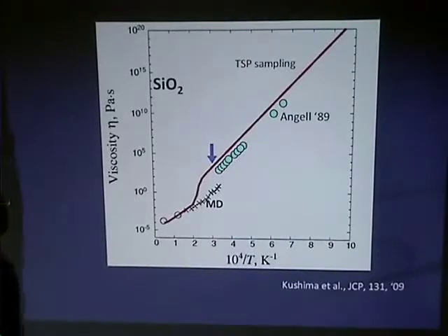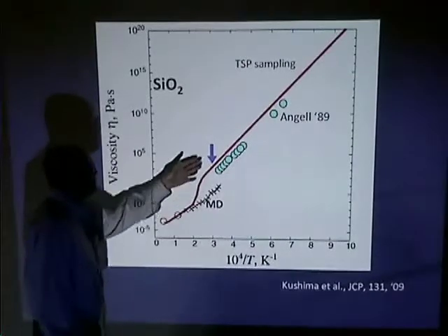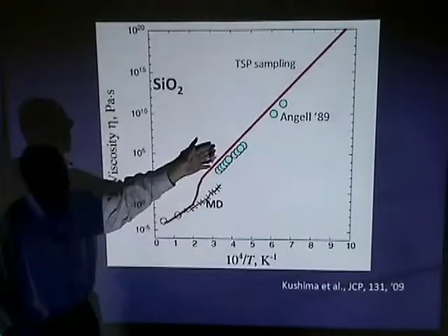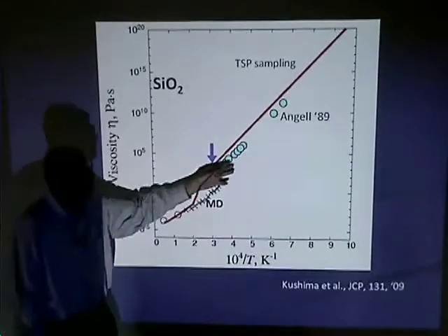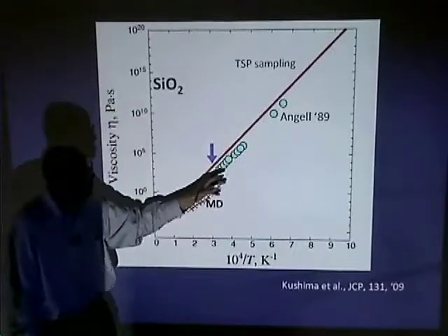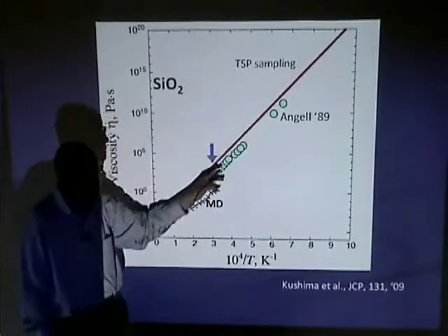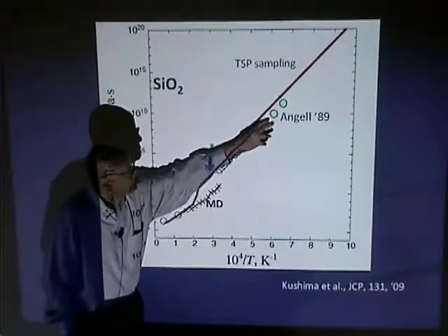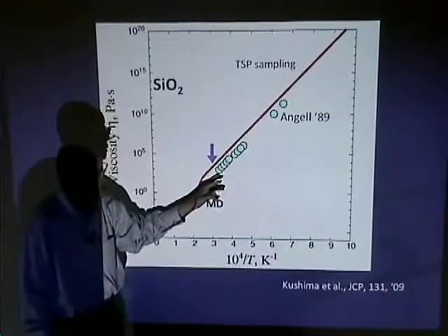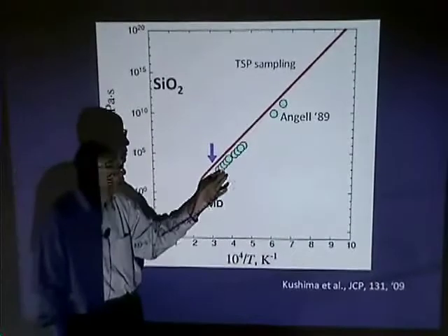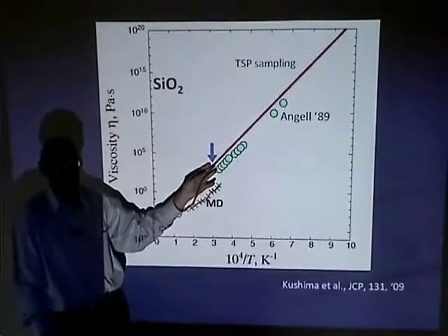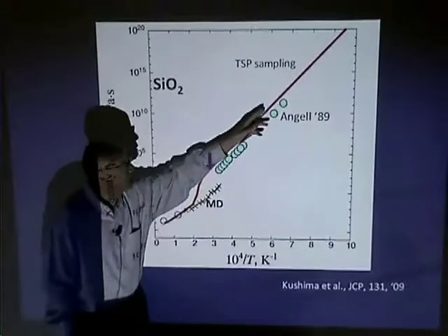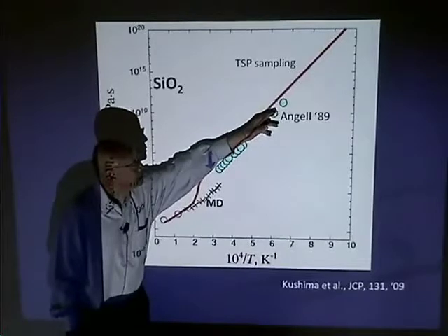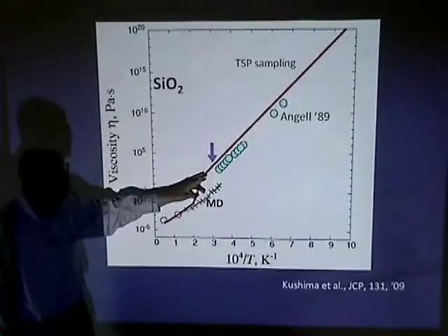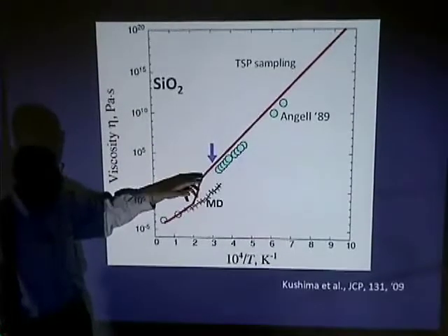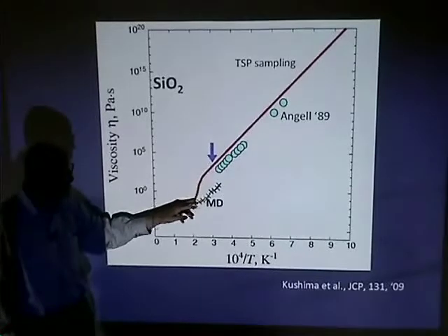Same thing, so the red curve now is our curve using this silica potential. And here are the Angel data. So here's the experiment, here's what we got. You notice Angel was motivated to call silica strong because the data didn't show anything that's non-Arrhenius. And while we do pretty well with our thing, we actually, from the calculation, predicted there should be a change.